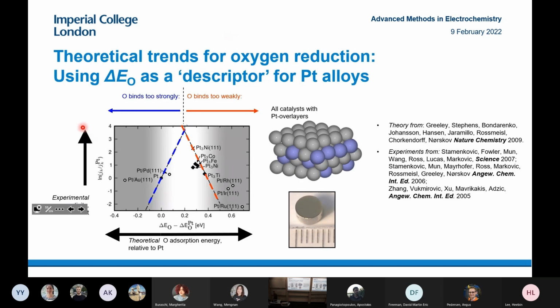So I've already shown you the oxygen reduction volcano. This is a zoom in, looking at different platinum alloys. These are typical alloys you use in a fuel cell, like in the Toyota Mirai. You have platinum cobalt catalysts. And you can see that, so this is experimental activities, then theoretical oxygen binding energy on a number of different surfaces from different groups. And you can see the overall trend follows quite well.